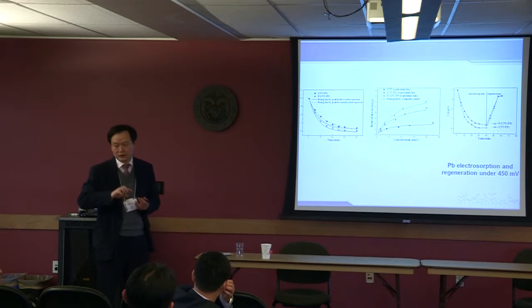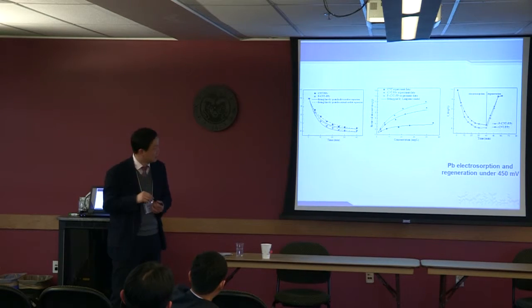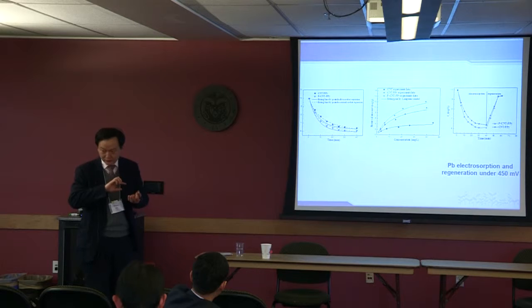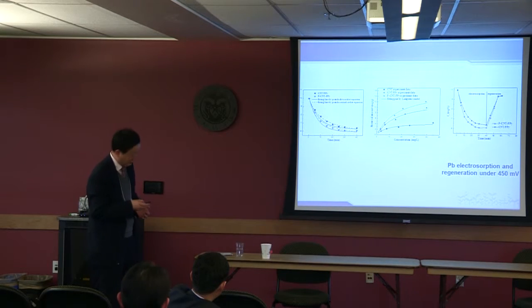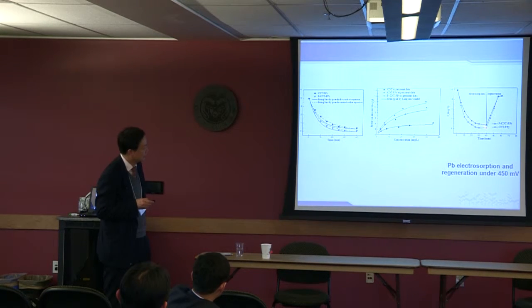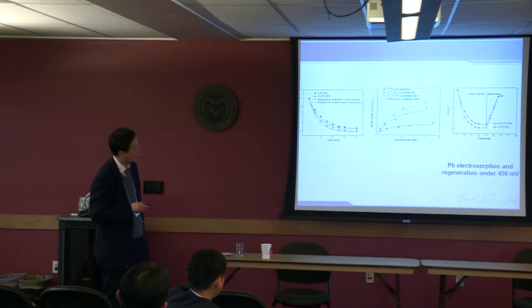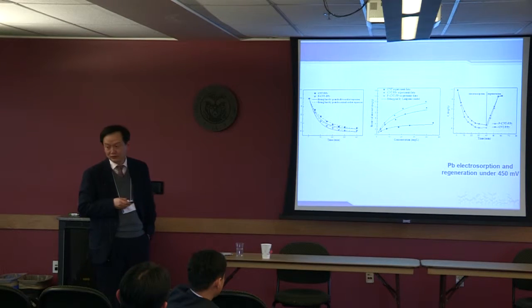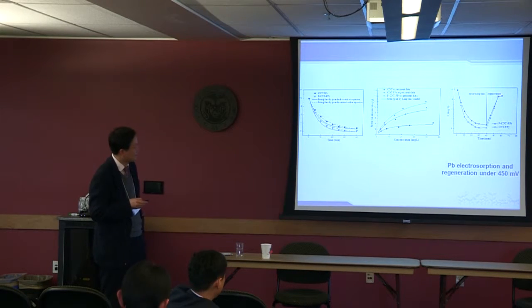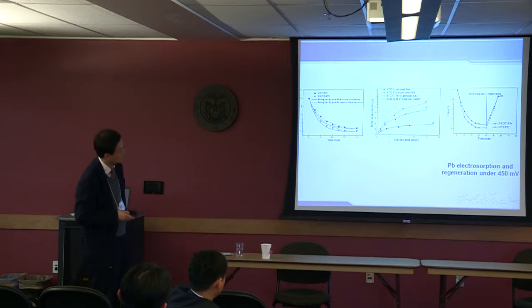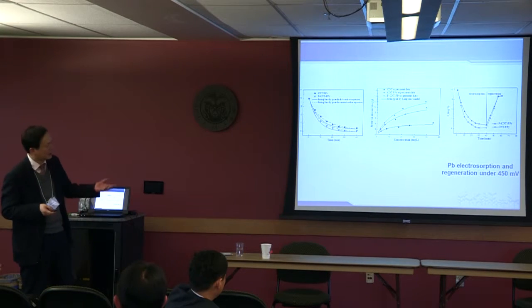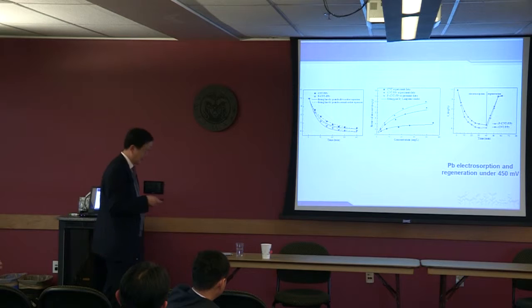Then we switch the positive and the negative, so the ions absorbed on the electrodes can be released into the solution at this level. So it's pretty good, very close to 80% or something like that.